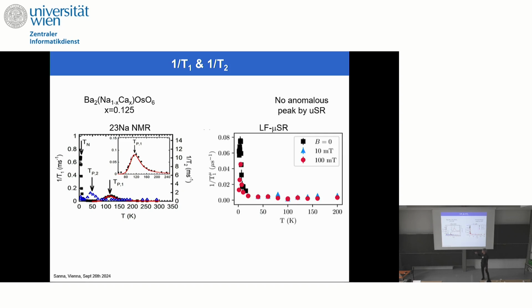Also the T2 displays a peak at lower temperature, because T2 is sensitive to the same dynamics, but at a time scale which is at a lower frequency. So the two peaks are related to the same dynamics. When we increase the temperature, the fluctuations increase, and then we first have a peak in T2, the transverse spin relaxation time, and then a peak in T1. Okay, so we discover a dynamical phenomenon